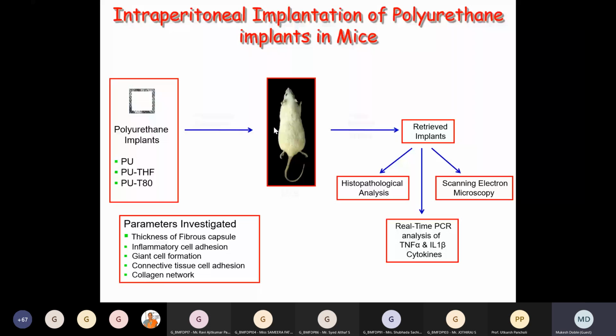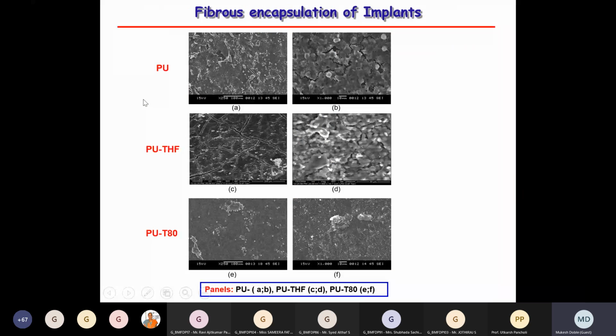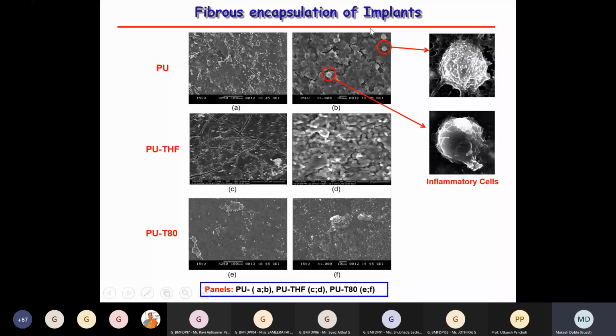Okay. So after 30 days, we looked at the fibrous encapsulation that's happening. The top one is the parent material, and you can see the bottom one is the surface modified material. Not much fibrous encapsulation has happened on the implant when compared with the unmodified polymer. In the unmodified polymer, we see a lot of inflammatory cells. That means there has been an inflammatory response because of the foreign material, whereas we don't see such inflammatory cells in the modified polymers which are implanted inside.